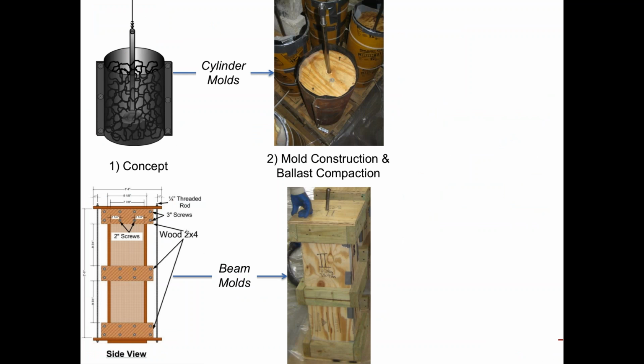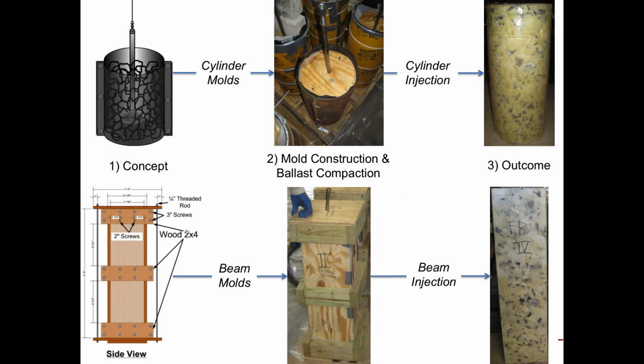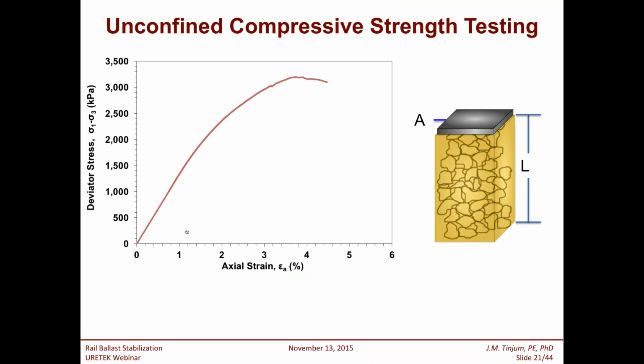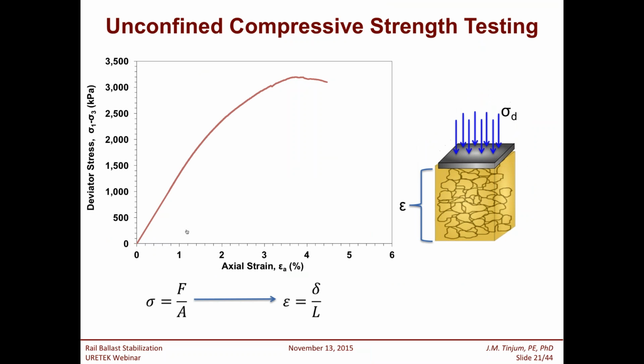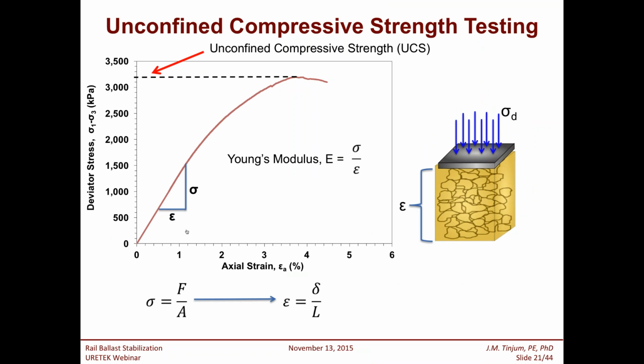What we do is we've got ballast that's coming from various of our rail partners here in the area and national rail companies. We have clean granite, rhyolite type ballast, dolomitic type ballast, a variety of ballast types as far as quality of the ballast and the gradation of that ballast. We put those into fairly large molds, and then we do injections here in the laboratory for beams and columns to test the material. Just as an example, the unconfined compressive strength is achieved by applying a load and measuring the deformation of that load, or that axial strain, and that peak strength would be called the unconfined compressive strength.